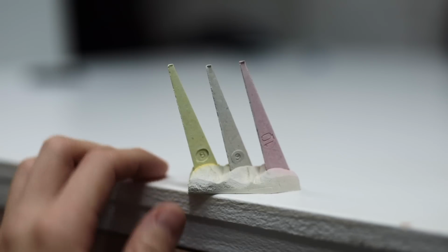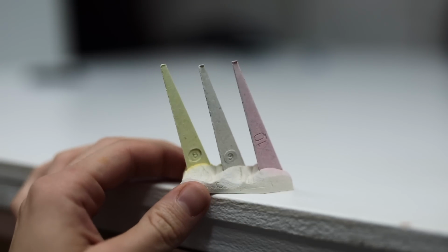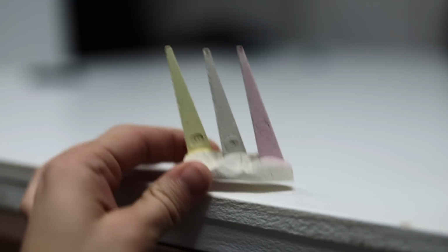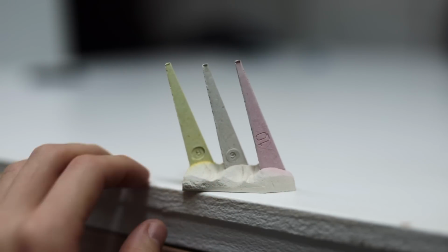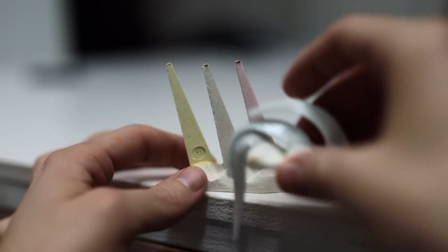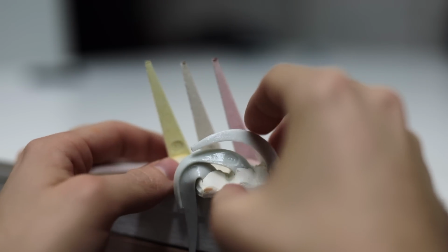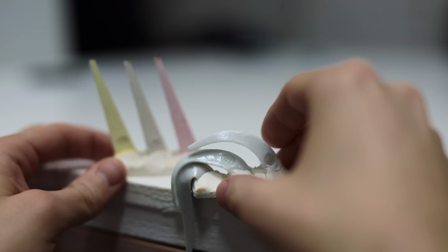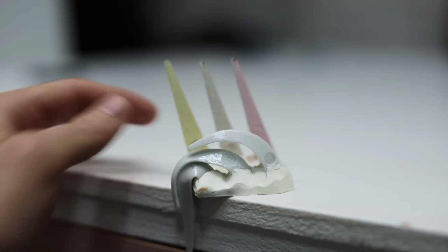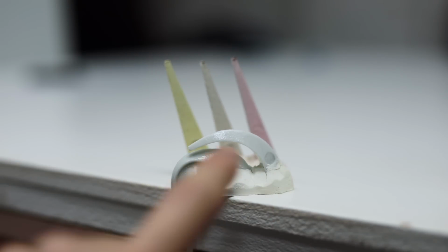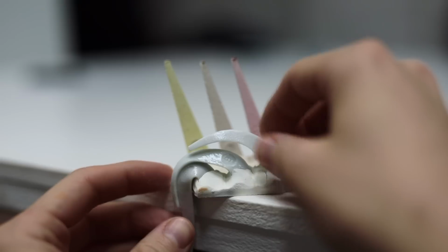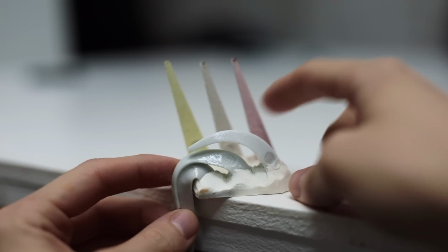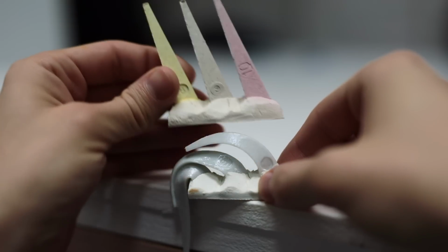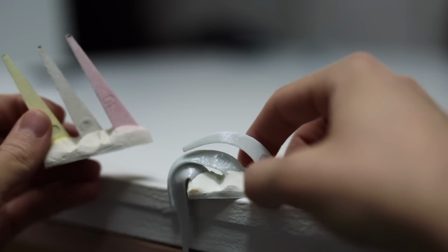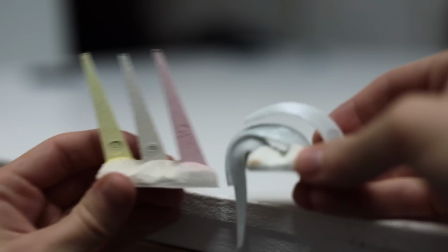The 3 colourful spikes you saw me place inside are called pyrometric cones. These melt and bend over at very specific temperatures, measuring the effective heat on ceramic over time. It's through these that I know when it's time to switch the kiln off, and when all 3 are bent over, like so, with cone 10 that melts around 1290 degrees, just about touching cone 9 in the middle. It's important to give the clay and glazes time to mature during the firing, and this often means sustaining certain temperatures for longer periods of time, and that's exactly what these measure.